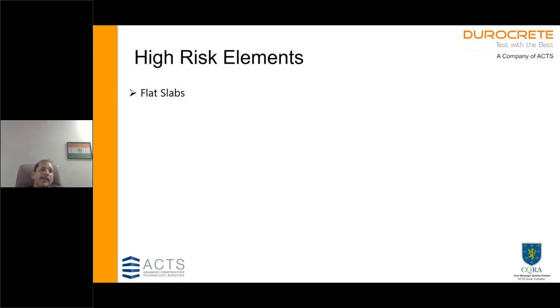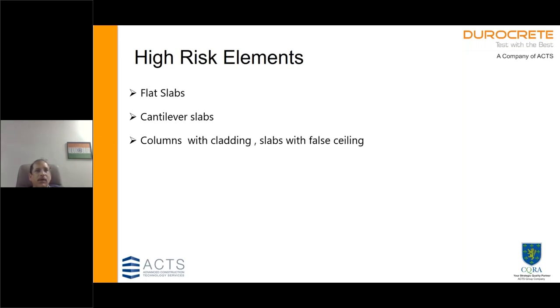So what are the high risk elements? The high risk elements are always the flat slabs, because they can fail in shear. The cantilever slabs, because the reinforcement is on the top. Many failures have been noticed because you can't see it from the undersurface, and many times the top is covered with a heavy layer of mortar and flooring, so it goes unnoticed. Then I mentioned slabs with false ceilings and claddings.